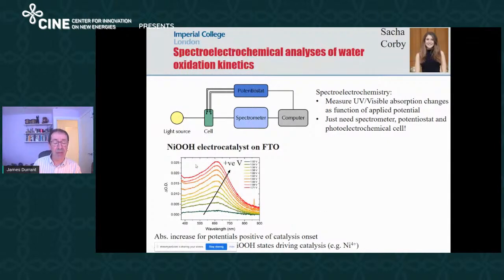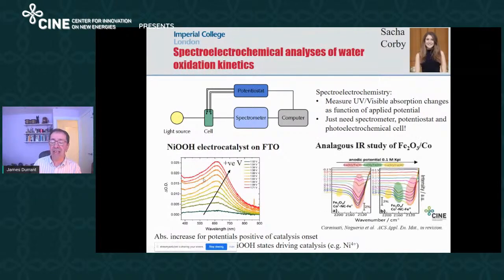This sort of spectral electrochemical approach using optical data is very similar to an approach which has been recently developed within CINE, as I've been very pleased to see. But in this case, here we're using infrared spectroscopy to look at some of the states involved, looking in more detail at the molecular nature of the states, in this case, on hematite surfaces with a cobalt co-catalyst. Infrared spectroscopy has more information on the nature of the states, but it's harder to quantify charge densities.